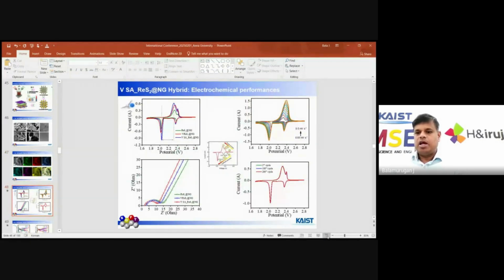After confirming the material, we do the battery performance tests. You can see this is the oxidation as well as reduction. When going for oxidation, the current density is higher, and the oxidation and reduction reversibility is very important. If oxidation and reduction are very fast, then it has higher catalytic activity for lithium polysulfide conversion, because it may prevent the lithium polysulfide formation, giving higher charging and discharging ability.